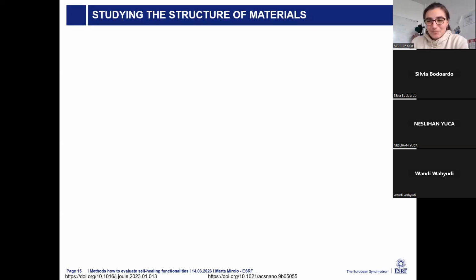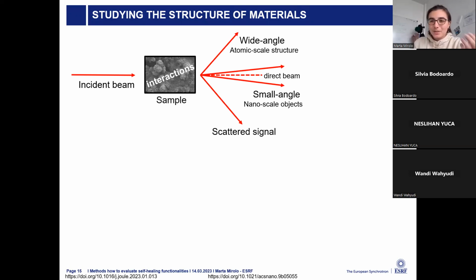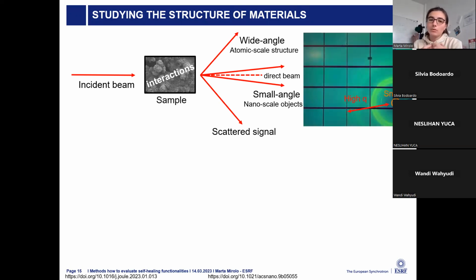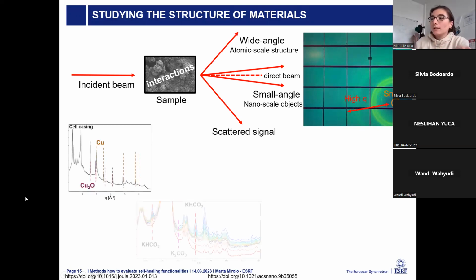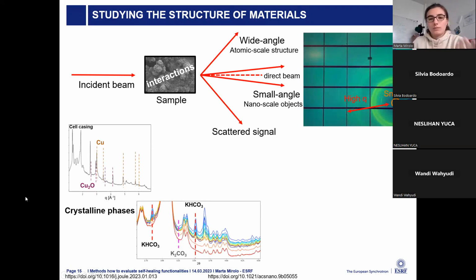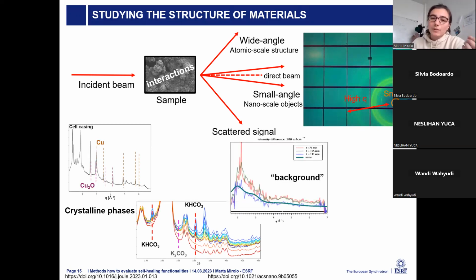And then the last example that I wanted to show is based on scattering techniques, in which we have an incident beam that is interacting with the sample. And then what we look at is the scattered signal. We can look at it in a wide angle or small angle X-ray scattering, in which we look at the structure from the atomic to the nanoscale level. And then what we can see is, for example, we can look at how the active material is changing, if there are new crystalline phases forming, but we can also look at, let's say, the background, especially when we are using high photon fluxes.